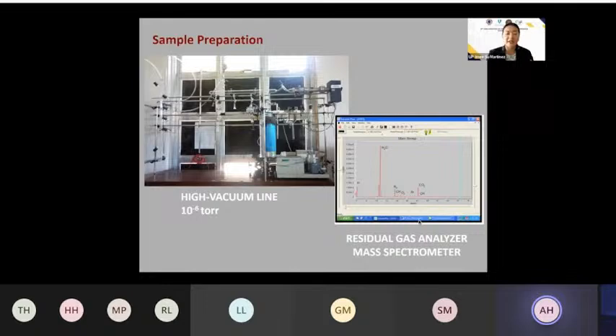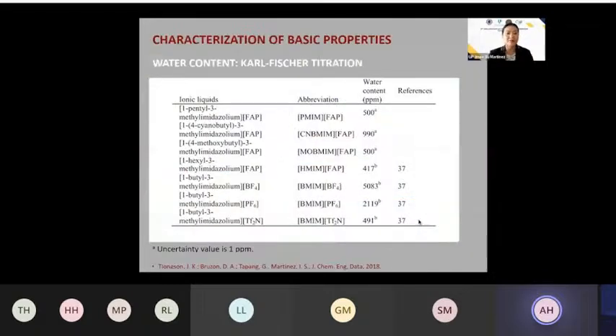This is a high vacuum line that goes up to 10 to the minus 6 torr, and therefore we are able to control the gas that we put into our ionic liquid, and it actually comes with an RGA, or residual gas analyzer mass spectrometer. So we are actually quite aware of what the volatile components present in the line are, and therefore in the headspace of our ionic liquids.